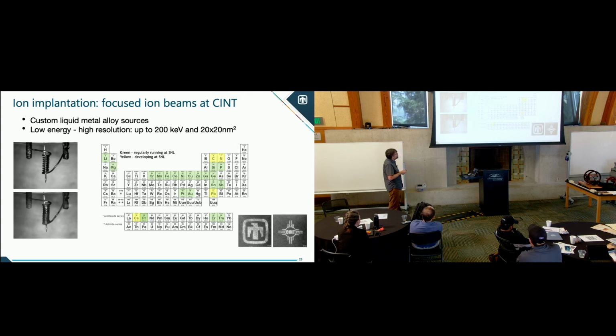This is the periodic table of things that we can do most easily in green and maybe in development in yellow. Now, nitrogen is hard because it likes organic things better than liquid metal alloys. So it's really hard to get into a liquid metal. We've shown a nitrogen beam before, but it's not that great. There's another group recently that has a plasma FIB that can do it and actually implant nitrogen with 50 nanometer resolution. We actually focus mostly on the group 4s because those are also interesting defects for quantum information sciences: the silicon vacancy, germanium, tin, and lead.